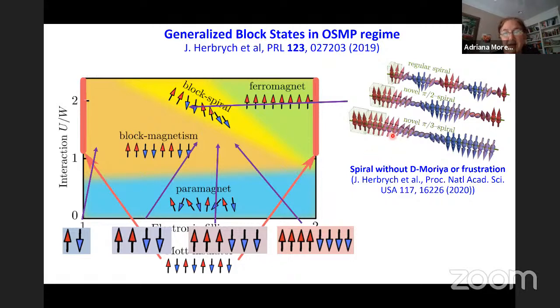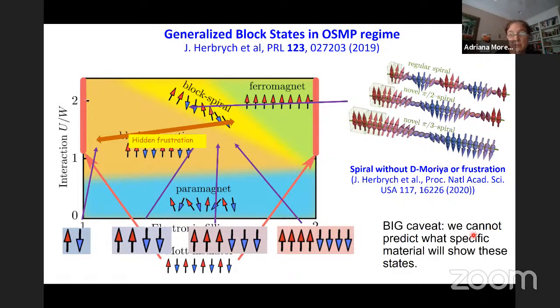This spiral phase appears in this multi-orbital Hubbard model without Dzyaloshinskii-Moriya interactions or frustration put in by hand. So there seems to be a hidden frustration arising from the competition between Coulomb repulsion and Hund coupling. This phase hasn't been observed so far, but we believe it could exist in some materials, though we cannot predict which ones. This is something experimentalists will probably have to try to find.